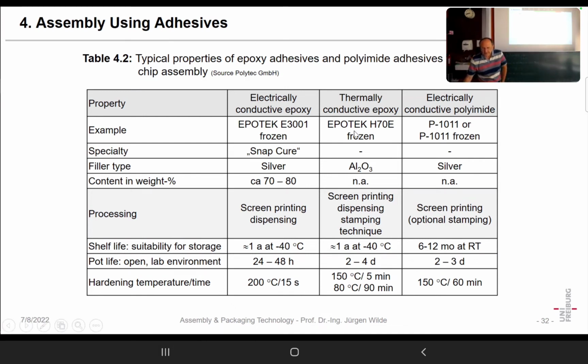And for instance, here you see that EPOTEK H70E, it is also frozen. It is not a snap cure. And for instance, here you see such conditions, 150 degrees centigrade, 5 minutes, or 80 degrees centigrade, 90 minutes. So these are just examples, but more or less most epoxies are in that range of hardening conditions.